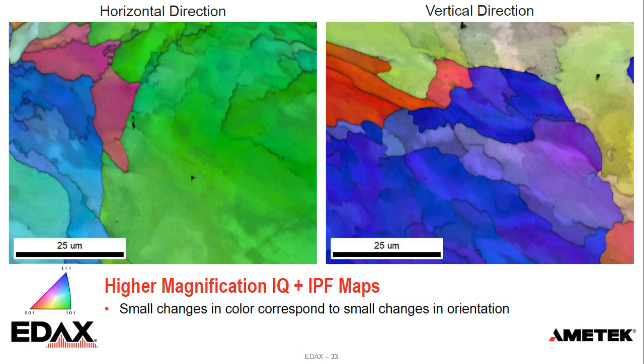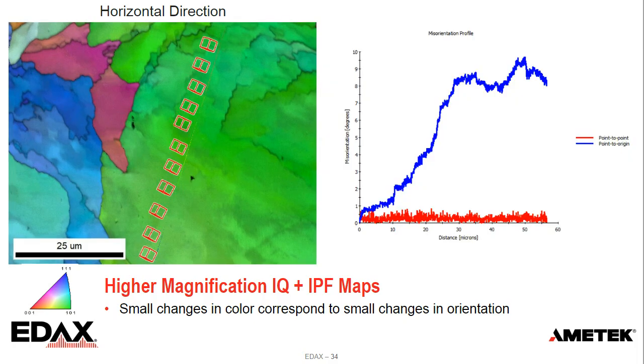And so if I look at this in terms of a misorientation profile, you can see on the left, I've drawn a line from the bottom to the top within that single grain. I've overlaid on there unit cells along that profile line. You can see that along the line there are small changes in orientation. And we can see that on the profile on the right, the misorientation profile.